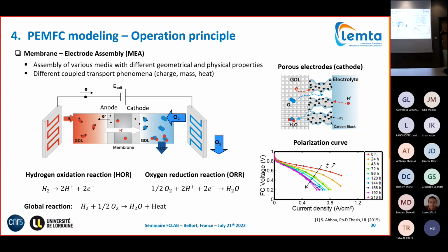operation. And the microscopic transport phenomena occurring in these materials underlie what we call the polarization curve. It means the evolution of the cell voltage as a function of the current density, which has a certain shape, shown here. At the lowest currents, it is primarily governed by electrochemical reaction kinetics. At intermediate currents, it is primarily governed by ionic conduction due to membrane hydration, and at the highest currents it is governed by mass transport, mostly oxygen transport phenomena.